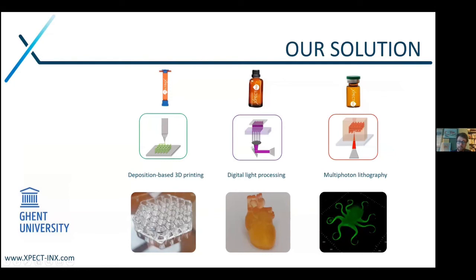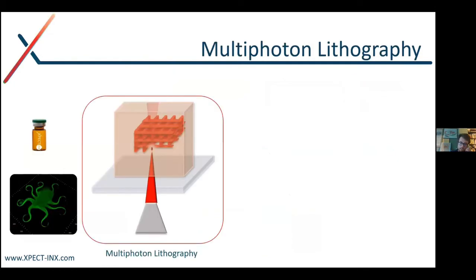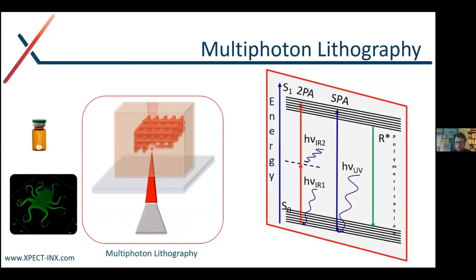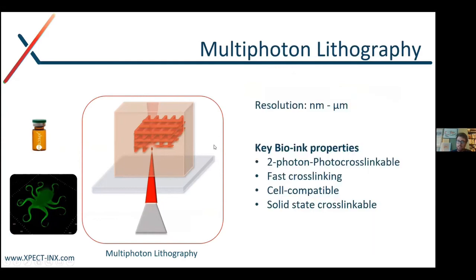You can go to the high-resolution multiphoton lithography. So multiphoton lithography is a high-resolution laser-based 3D printing technology, which is based on the simultaneous absorption of 2 near-infrared photons, as opposed to single photon absorption in most light-based technologies. And this has the benefit that polymerization can only occur in a very small volume element, which you can scan freely in 3 dimensions, creating very high resolution, and also a lot of architectural freedom. Now here the resolution is in the nanometer to micrometer scale, and also here there are some key bioink properties.